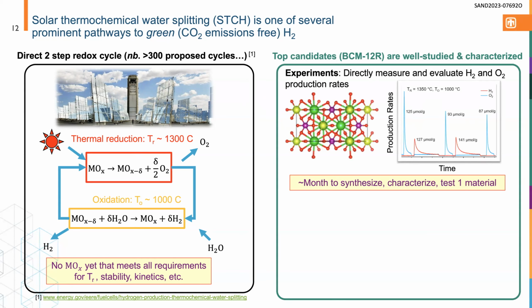So the issue is really that nothing has been commercialized here in terms of STCH hydrogen production. That's because no metal oxide yet meets the requirements: a sufficiently low thermal reduction temperature, sufficient stability, fast enough kinetics, cheap enough, all these different issues. But there are some candidates that are pretty high performing. One material that's been looked at extensively at Sandia is this BCM12R structure, and you can see on the right those are pretty decent hydrogen production rates. But again, it takes months to identify a new material, and if you're randomly guessing which metal oxide might work for this application, you're going to be in trouble.